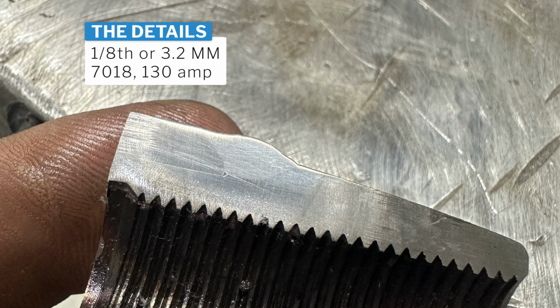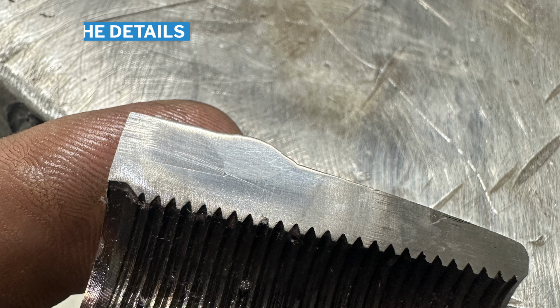Let's look at the 1/8 inch rod now. So this was run at 130 amps, and you can see the bead profile is very similar to the 3/32 rod. It's a little bit wider. This is the ideal profile that you would want to see with a 1/8 inch rod. And once again, you can see that very minuscule lack of fusion there down right at the root, which again isn't too much of a concern, and if it is, you would have to run more of a gap so the weld metal would more or less hit that better.